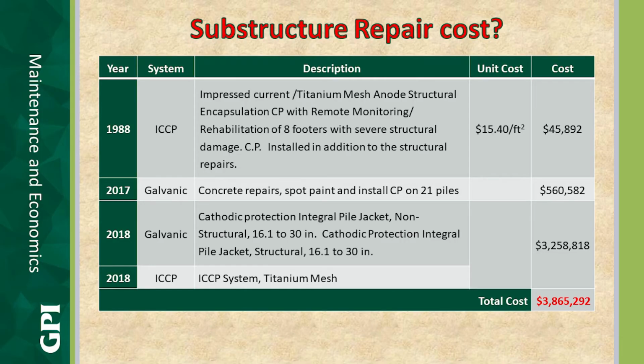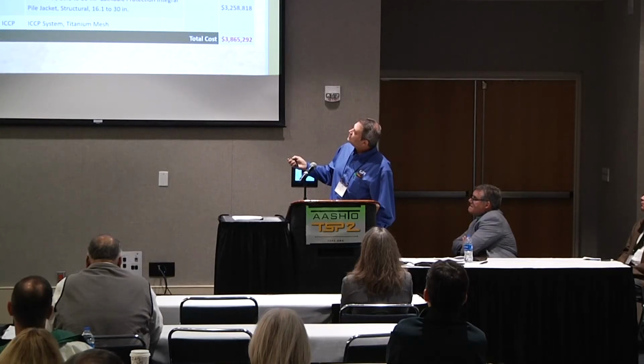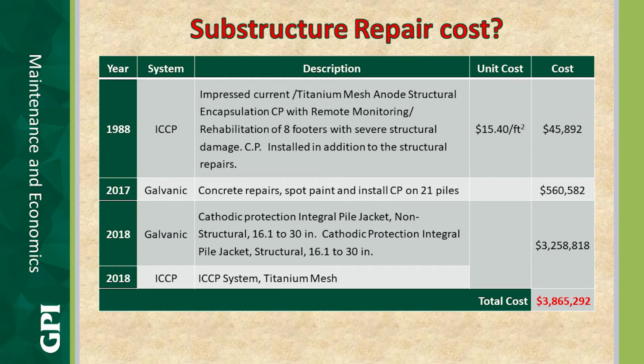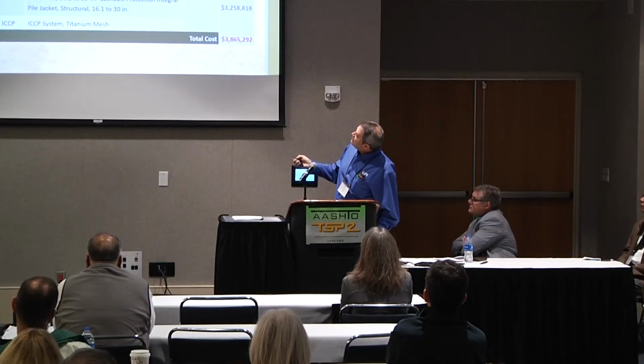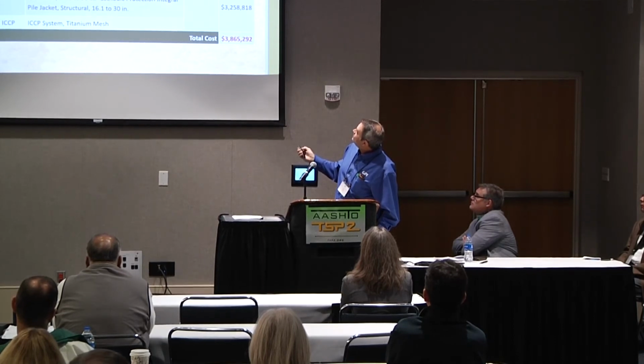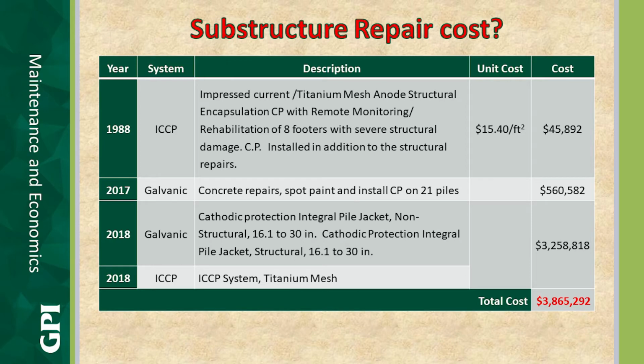Well, how much did all this cost? That's the money rules everything, right? So in 1988, FDOT installed impressed current cathodic protection systems. They encapsulated CP with encapsulation, and I apologize, these are quick notes out of FDOT spreadsheets, so the grammar and language isn't necessarily the best, but they rehabbed 8 footers with severe structural damage, and CP was installed in addition to the structural repairs. It cost $15.40 a square foot for a total of about $46,000 in 1988. Going through, we've got some concrete repairs, spot paint, and install CP on 21 piles, a cost of $560,582 in 2017.